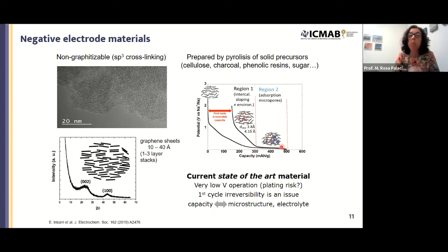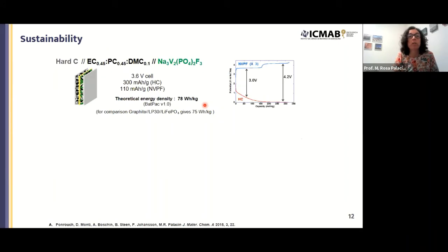It has a very low operation voltage, slightly lower than graphite, so there is some risk of sodium plating, which needs to be mastered. And the main issue with this material is that there is a lot of irreversible capacity on the first cycle, but this can be tuned typically by tuning the microstructure, which is in turn determined by the pyrolysis conditions, and the electrolyte used also has an effect on this.